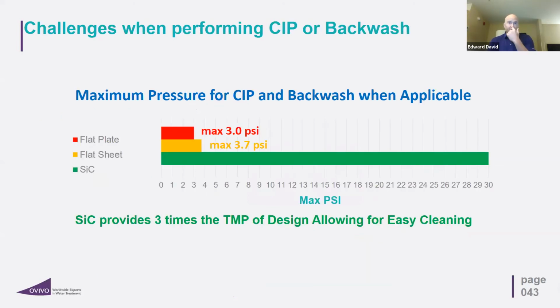Max pressure. What is max pressure? Well, when you're processing water and then you hit that routine maintenance clean, you're actually sending water back into the membranes with chemical. And if you're lucky enough to have the ability, you're sending backwash back into the membranes with no chemical. Flat plate, maximum 3 PSI. Maximum pressure on flat sheet, 3.7 PSI. On SiC, you can get up to 30 PSI.